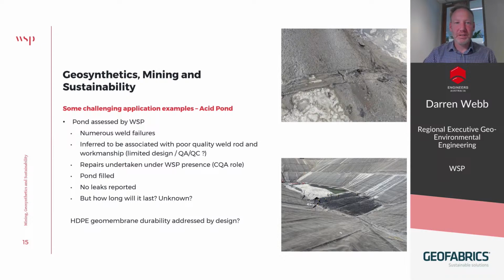So they called in WSP to have a look at the geomembrane after the pond had been dewatered for the second time. What we observed was numerous weld failures, primarily associated with extrusion welding, and we inferred that to be associated with poor quality weld rod and perhaps workmanship from the welding. You could draw a line that's associated with limited requirements related to those two components in the design documents. What did the design require with relation to weld rod and welding installation requirements?